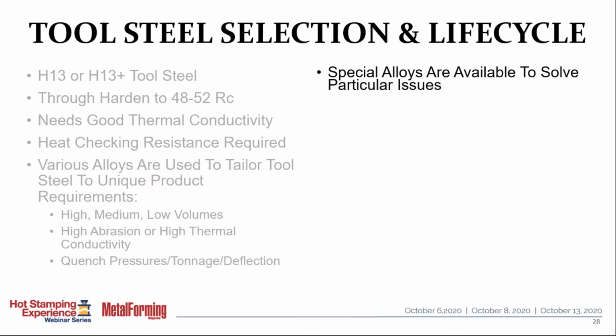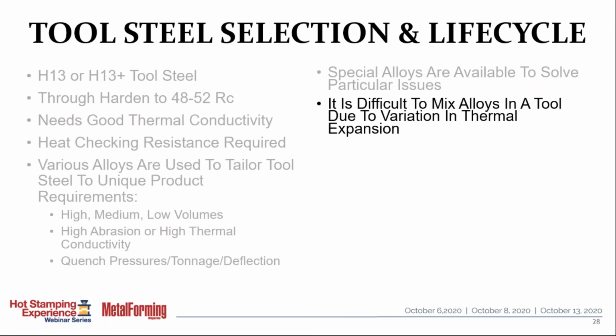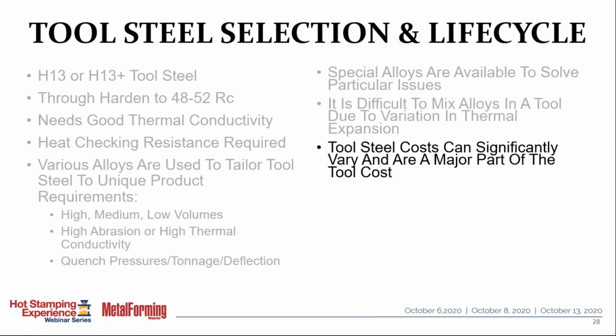There's also special alloys available to solve special issues. However, we typically try to use one alloy in the tool all the way through it rather than combining alloys because of differences in thermal expansion and people mixing up steels when they may maintain them.